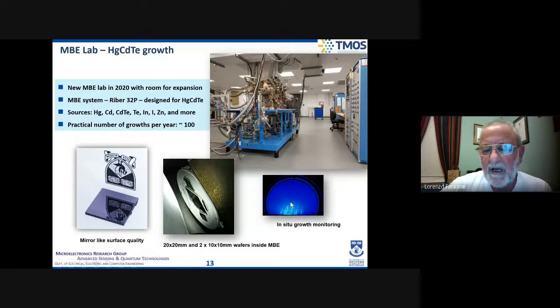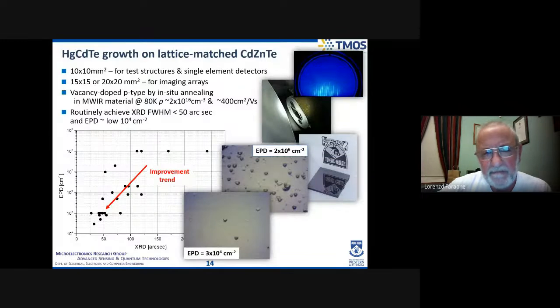We have in situ RHEED as well as other diagnostic tools on the MBE machine. The layers are typically characterized primarily for defect densities, because in the end you're trying to make an imaging array. So typically for imaging arrays, we would grow on a 15 by 15 millimeter or 20 by 20 millimeter substrate.